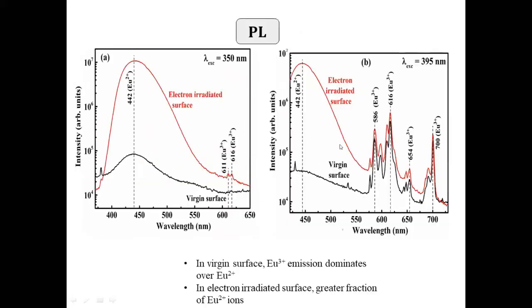So here you see the exciting wavelength is 350 nanometers, and the electron irradiated sample emits light mostly at 442 nanometers. Broad band is seen, and the light emitted in the red part is much less, almost 10 to 20 times less. So it is a blue light source.